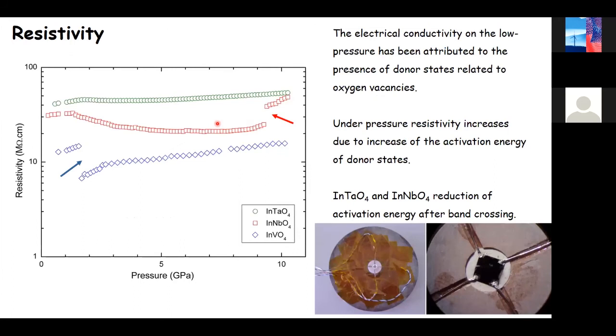Okay. In addition to that, let me summarize. We have found by Raman and X-ray diffraction one phase transition in each of the compounds, and in each of them, the phase transition is inducing a coordination change either in vanadium, niobium, or tantalum. This change will produce a collapse of the band gap in the 3 compounds. This also should produce a change in the electrical properties, and we have done it here in resistivity measurements.